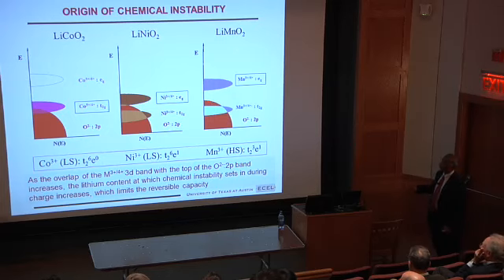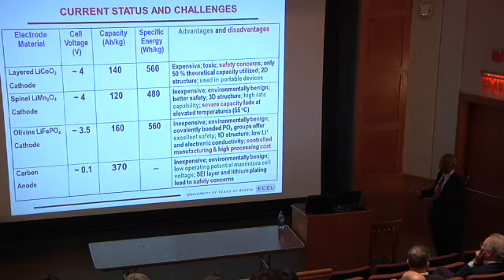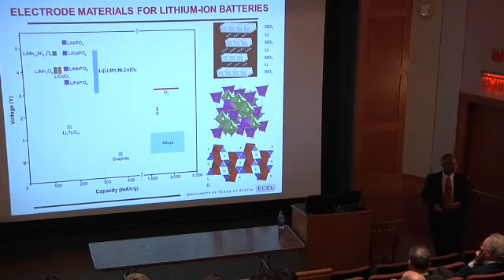But why don't we use this? Why are we using this? A lot of other issues. When you charge it, it will transform from the layered structure to this spinel structure. So that's the problem. Why does it transform? The transition metal ion can easily migrate from an octahedral site to a tetrahedral site to this octahedral site because of less octahedral site stabilization energy for manganese.